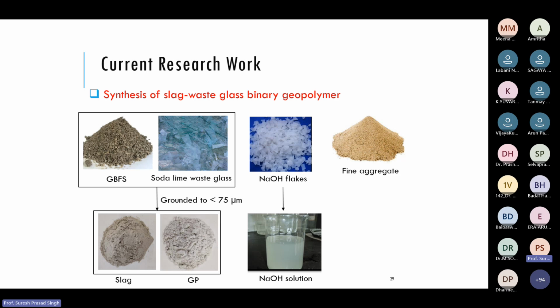This is one of these things. And the second thing we find is that the production cost will be reduced, since I will be using this soda lime glass so that the consumption of fresh sodium hydroxide or sodium silicate will be reduced. And soda lime glass contributes silica. We require more silica than alumina, in the ratio of 2 to 3. Getting silica from soda lime glass is easier than getting silica from this slag. So it releases silica.